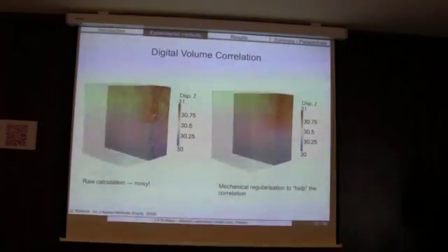So this is what it looks like, and unfortunately that was bad news, because when we said we want to measure the K values along the crack front, not having a larger fatigue sample that we cut, then you end up with very small cracks. And those very small cracks give you a very noisy signal in correlation. And you can see it here. It's cut within one sample. You see it's very noisy.